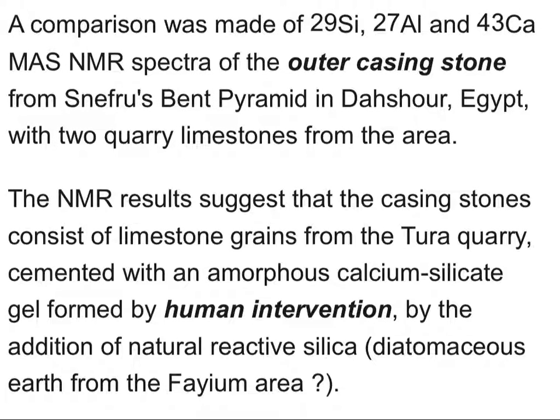The NMR results suggest that the casing stones consist of limestone grains from the Tura quarry, so we have natural limestones that are cemented with an amorphous calcium silicate gel formed by human intervention by the addition of natural reactive silica, diatomaceous earth from the Fayum area.